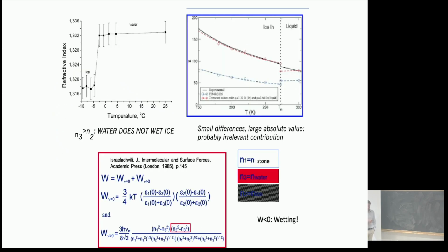What I also showed you is that we know the refractive indices and dielectric constants of water and ice. Those of glass, because glass is what we're going to use, we can also use, and this is what I call stone here. If you do the calculation, you find the Hamaker constant is negative, and so that tends to separate the two surfaces. And I anticipate that in my pore there will be a wetting film.